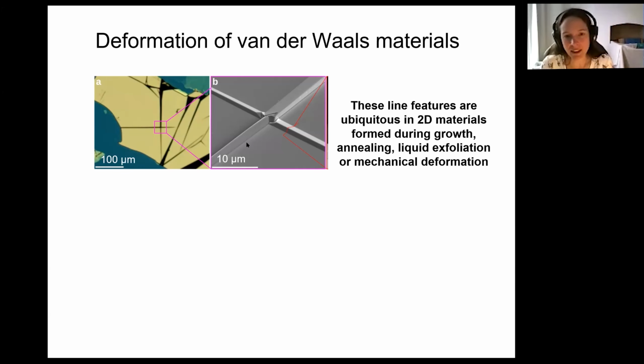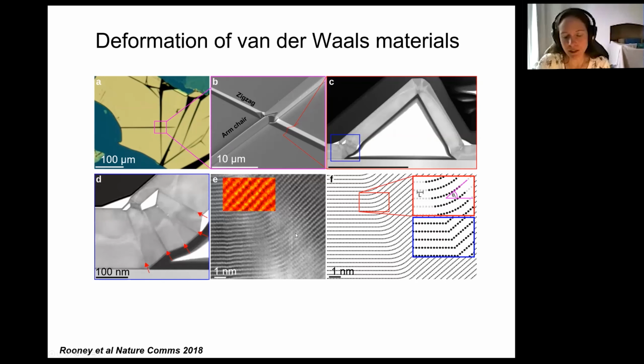Okay, so having a look at these kink band defects that we can see in the optical image in A and the scanning electron microscope image in B. To investigate these, we've used the focused ion beam to dig out trenches on either side and extract a cross-sectional lamella through each of these types of defects. So what we see when we do that is shown here. C is low magnification, then we zoom in D, and again further over E.